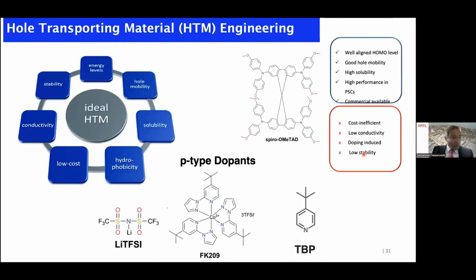Now I come to the hole transporting materials. So far we have used spiro-OMeTAD, and this has several issues. The mobility in this spiro-OMeTAD is not very high, so we have to dope it with cobalt complexes. It partially oxidizes, about 10% of the hole transporting material, to increase the conductivity. And it also has lithium TFSI and tert-butylpyridine. All these dopants actually promote the instability of the hole transporting material.